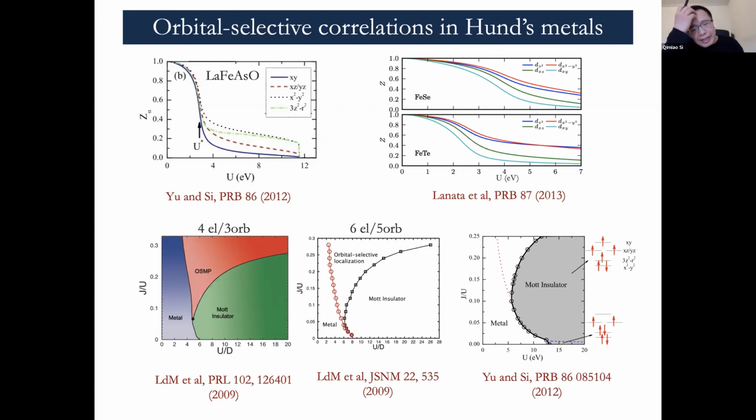Yeah. So, but let me actually put a question to you. I was a bit surprised when you said that the correlation is moving the XY orbital filling further away from half filling, because we always found the opposite. Yeah, in fact, in our HSE calculation, it's slightly less correlated. So I think this is some mechanism that we stressed a lot and isolated in these very first papers, that we called orbital decoupling.